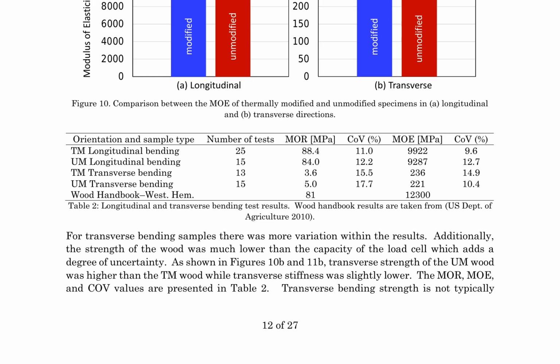Results for transverse bending, Table 2, indicated higher transverse strength for unmodified wood and slightly lower transverse stiffness. The study's findings highlight the impact of thermal modification on the mechanical properties of wood, particularly in the longitudinal direction, and emphasize the importance of considering regional forest characteristics and tree growth patterns when evaluating wood properties.